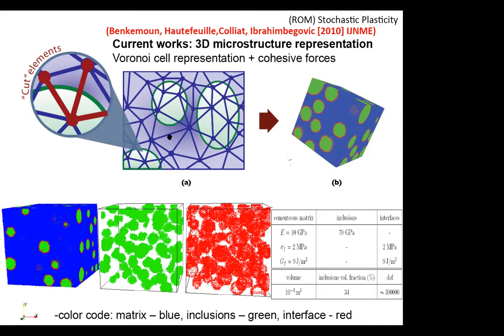together. So at the microstructure level, we're going to be representing the failure modes, not by the finite elements this time around, but by Voronoi cells. Why? First, Voronoi cells are much faster to build the mesh. Secondly, this is one of these discrete models which will represent isotropic linear response. We are not after linear isotropic response, but in any case, we have to start with that because before going into hardening and fracture, you first have to be elastic, preferably isotropic and linear.